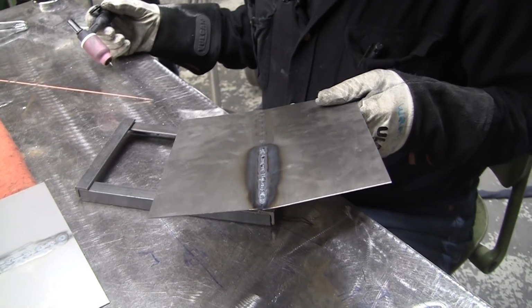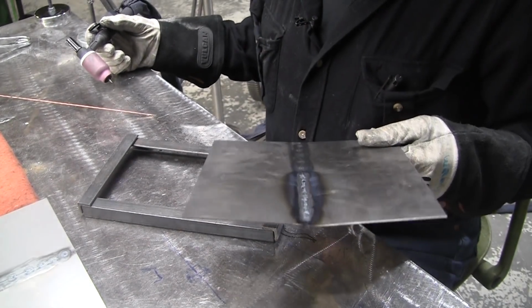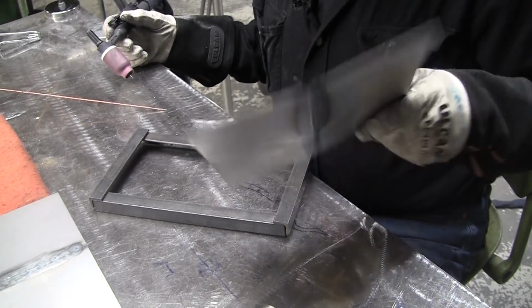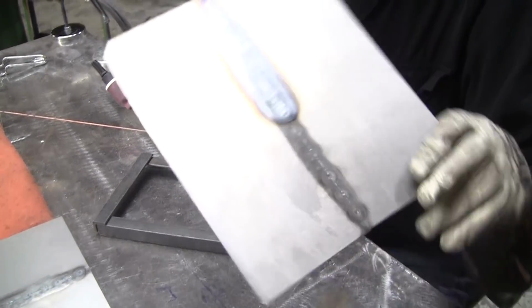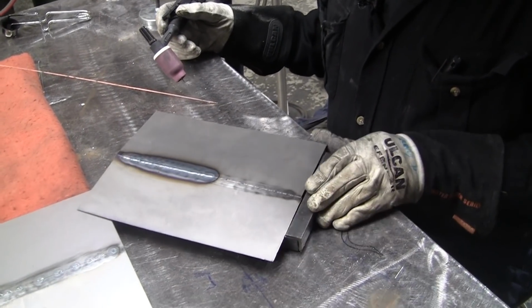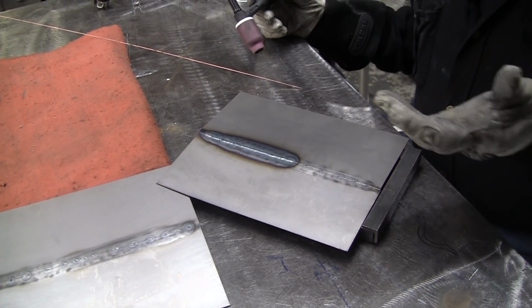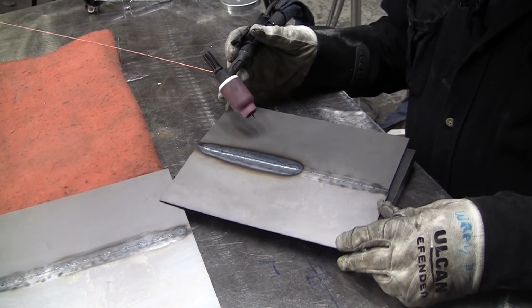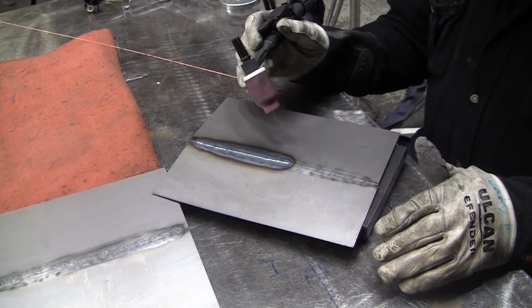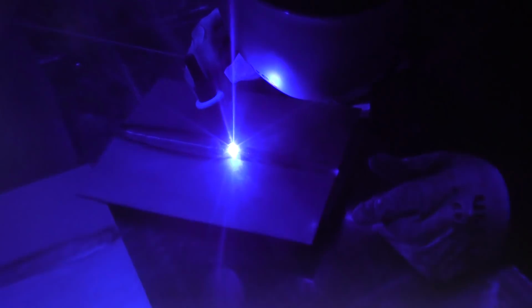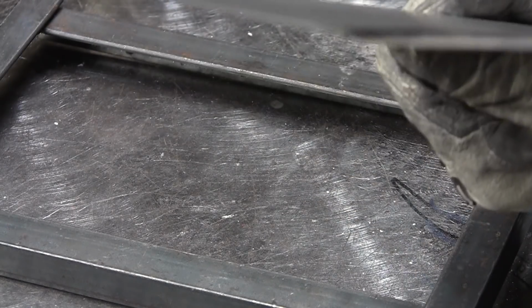That's typical because the oxygen is attacking that a little bit on the backside. If we coppered that, the weld would look as nice as the front side. So another time we'll try the copper on there. The copper blocks the oxygen off the weld, gives you effectively like a backgas condition. Now, we're going to fusion this the rest of the way. I just want to check it to make sure I got enough heat there. Yep, looks really good.